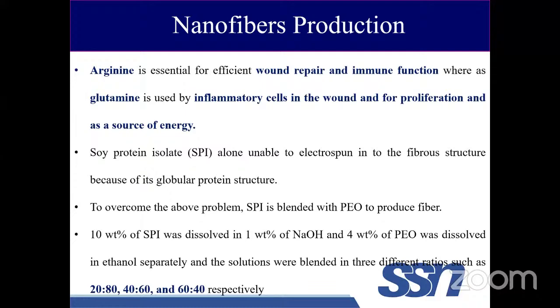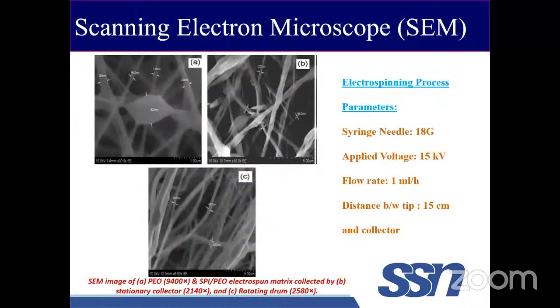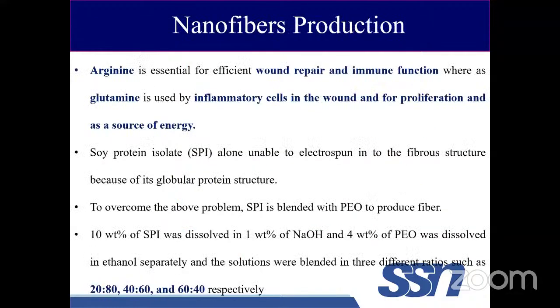So that is the reason we blended it with polyethylene oxide to convert it into a fiber. Here PEO is a fiber forming agent, right? So what we actually did is we took 10% soya protein isolate in 1% NaOH, and 4% of PEO was dissolved in ethanol. We blended this solution in the ratios 20-80, 40-60, and 60-40.